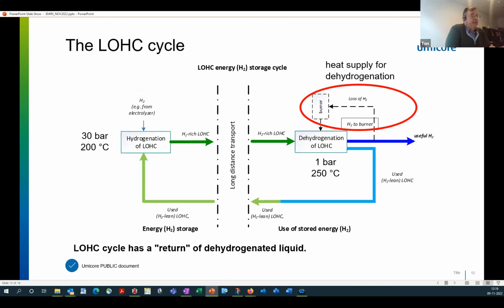With this hydrogen-rich LOHC, it's a stable molecule, it's oil. Yeah, you can transport it over long distances and so on. And once you use it for dehydrogenation, I have drawn this here, you get your hydrogen out, but you have to use a part of the hydrogen to keep the dehydrogenation reaction going. Yeah, it's essentially the same problem as with ammonia and also with the solid hydrogen storage materials. So a solution to that is just to install a burner to heat the reactor and use a part of the hydrogen that you have released to keep the reactor warm.